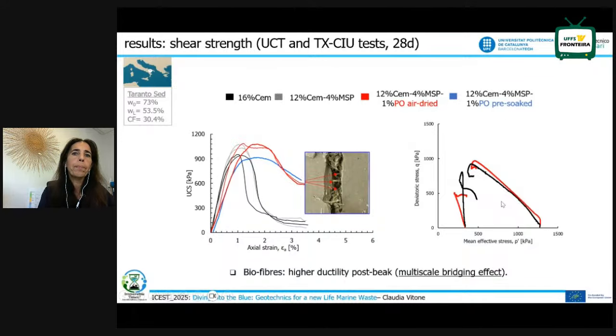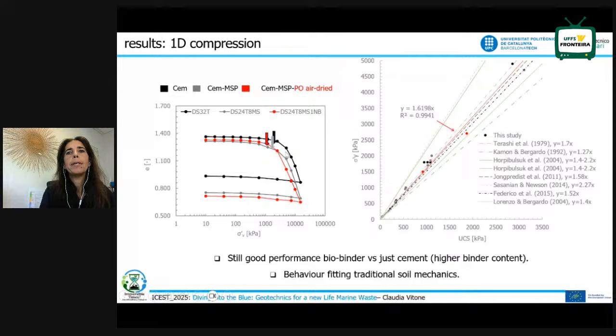These are consolidated and drained triaxial tests, and again you can see here a result in the q-p' plot of the control mixture and the mixtures with the fibers and the shell that is essentially behaving in a similar way. These are again odometer tests. Again, you can see that with shells and fiber, the story is still the same, and also the correlations with the literature data working on traditional mixtures with cement or lime and clays are essentially in the cone of the literature for these mixtures.